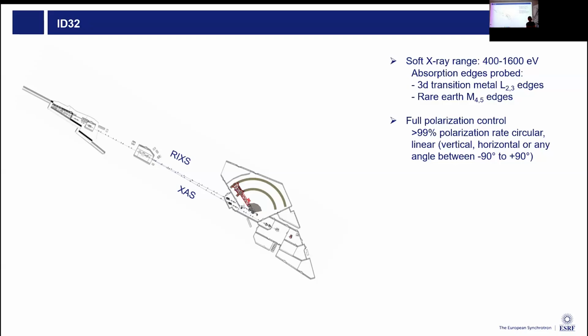Our X-rays fall between 400 and 1600 eV. This means that we're well suited for the L edges of transition metals, the M edges of rare earths, and we can also do K edges of nitrogen and oxygen. Our flux at low energies is not fantastic. We really were optimized for copper and above. So that's something to keep in mind if you want to plan an experiment with us. We do offer full polarization control, 100% practically circularly polarized, as well as linear vertical, horizontal, and any angle you would want in between.